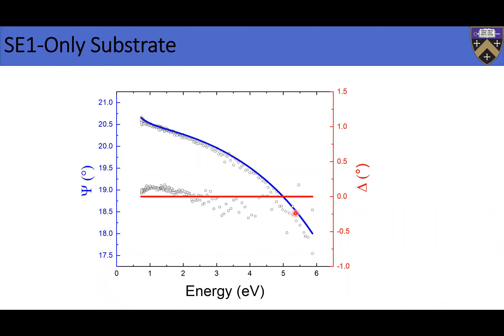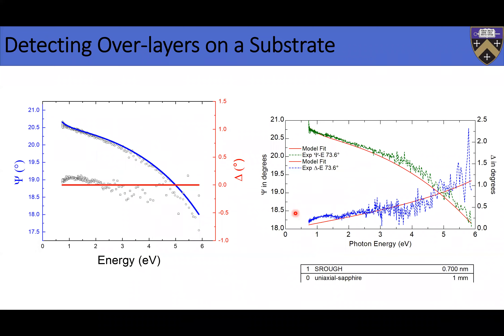Once we get this match, we know the substrate is behaving well. Sapphire is uniaxially anisotropic — most people grow on the c-plane. If there's a small misalignment in the c-plane, you can catch that with this particular spectrum. If I can't model it properly using a c-plane orientation, I know that the substrate is probably off-cut. I want to show one other thing: here is another sample where when you look at delta, you find that you cannot fit delta with a straight line — it's not zero.